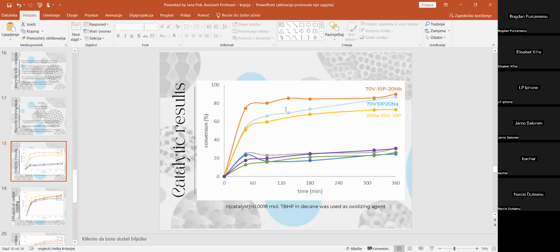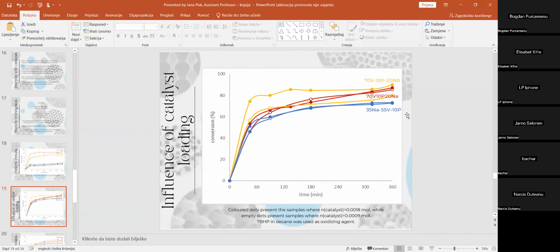When we diminished the amount of vanadium to 55%, we also got an active compound, but less active than with 70% of vanadium. Then we tried to compare the oxidants, and we used TBHP in water and TBHP in decane. Sorry, here are the results with TBHP in decane. And we tried to diminish the quantity of the catalyst to half, because we wanted to see what will happen with the activity if we diminish the catalyst loading.